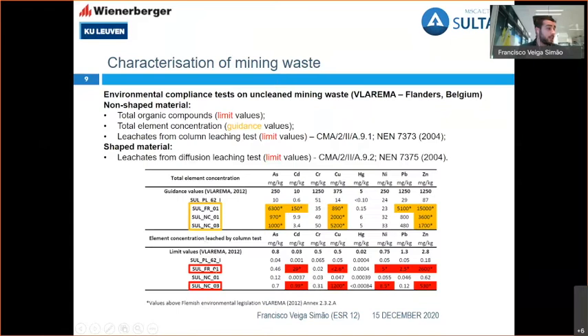On this, you can see the Freiberg tailing and the Neves Corvo stored. The main difference between 1 and 3 is that waste rock 1 is fresh material and 3 is stored material in an open stockpile. And both of them go over, so they cannot be certified as granular material. Nevertheless, they always have a chance, because they didn't go over the organic compounds, to be integrated into a shaped material and do a different leaching test, the diffusion leaching test, which is another test for the shaped materials. And if it passes, you can definitely integrate them into shaped products.